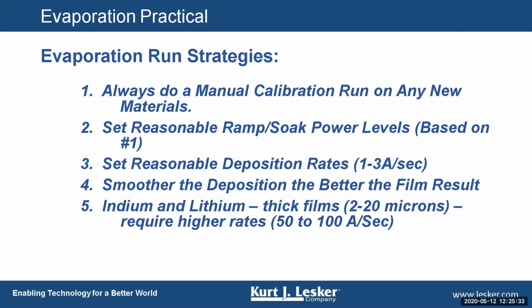Evaporation is always done in tandem or in cooperation with a quartz crystal monitor. The quartz crystal monitor is calibrated as well to read a relative rate. And then in an automatic feedback or PID loop control, the quartz crystal monitor will tell the evaporation power supply how hard to run, how light to run, based on the reading of the quartz crystal monitor.